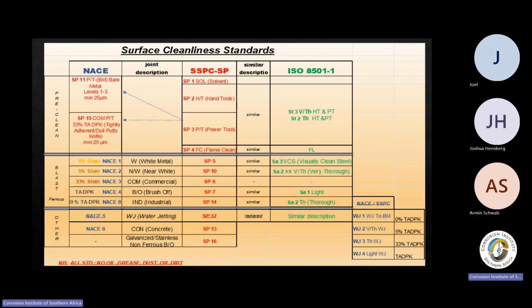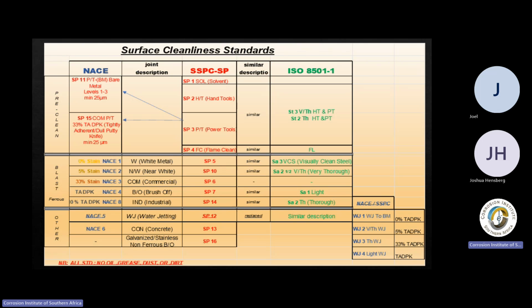That should, and I'm saying should, I'm winking at the coating suppliers, be put in the product data sheets, that when the relative humidity is between these brackets, that's how long you have to put it on. But it's temperature and relative humidity dependent, so there's no real given. A good rule of thumb in the industry, they tell you 6 hours. But now you've got a polyurethane coating, and that polyurethane coating has to be put on the surface within 3 hours after blasting. So it's dependent on product to product.